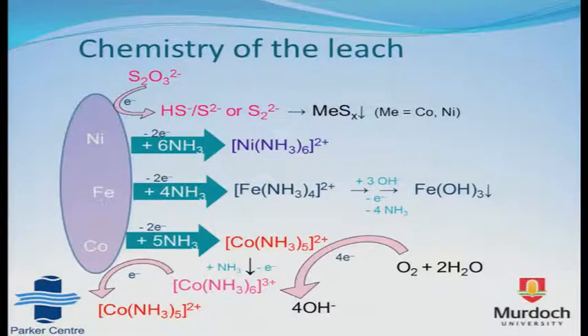The chemistry of the leaching is quite complex, but the main reactions taking place are the dissolution of metallic nickel, which is taken into solution by forming nickel amines. Cobalt as well goes into solution and is oxidized to cobalt-2 amines, which are then further oxidized to cobalt-3 amines, which also act as an oxidant, so further oxidize more metallic nickel and cobalt. Iron is also brought into solution, during any metallic iron present, by forming amines, but then further down, when the tanks are aerated, it is oxidized to iron-3 hydroxide and precipitates out, hence the selectivity of the process. It rejects the iron by precipitation.